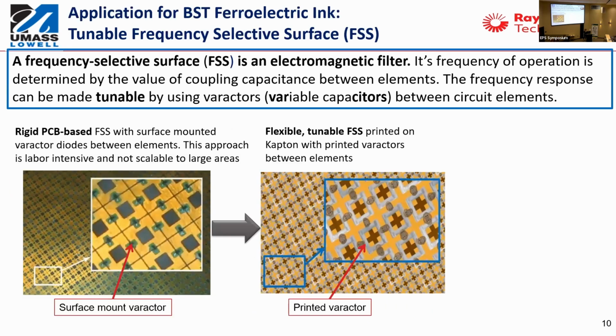Where did we use this? So this was one of our earliest projects with Raytheon, where we wanted to go from a rigid FSS structure that had surface mounted varactors and make it fully printable and on a flexible substrate. So what you see in the middle is the FSS structure that's tunable. It's actually printed on both sides. The design is a metamaterial design that's less prone to angle of incidence, so you can get fairly good performance even when you're bending it.